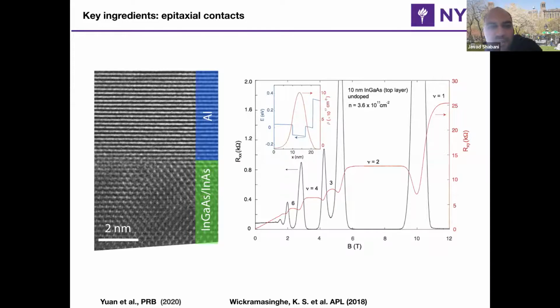And it turns out, if you go back, in 2015 and 16, it was developed in the context of Majorana fermion that you can make epitaxial contacts to the semiconductors. In particular, aluminum was a great match that we could find this domain matching to indium arsenide InGaAs structures. And if you ask, what is the quality of indium arsenide, you can see a quantum Hall trace on the right-hand side of this graph. That Rxx as a function of field shows various integer states. As we discussed, there are no fractions. Temperature is taken at 20 millikelvin.